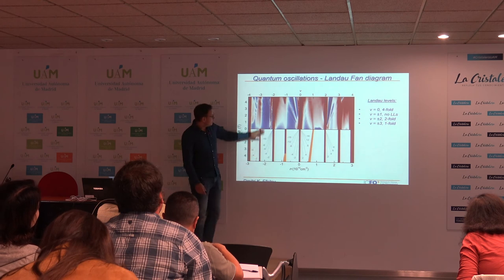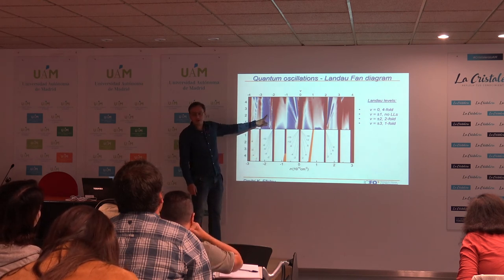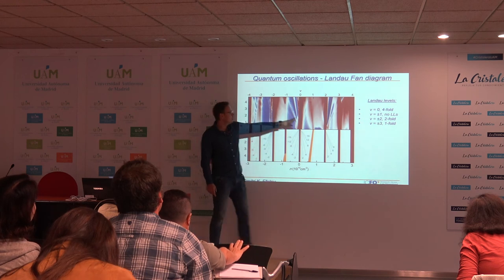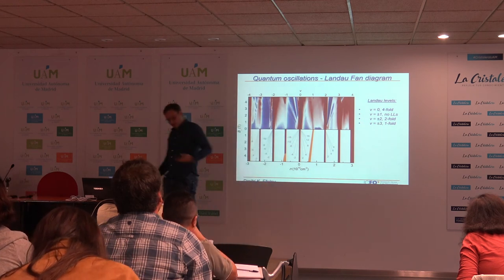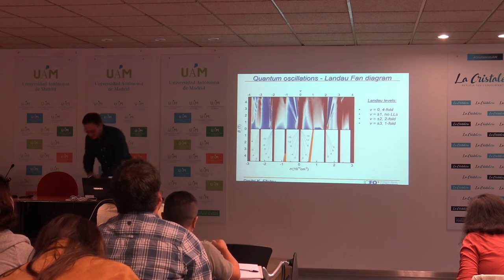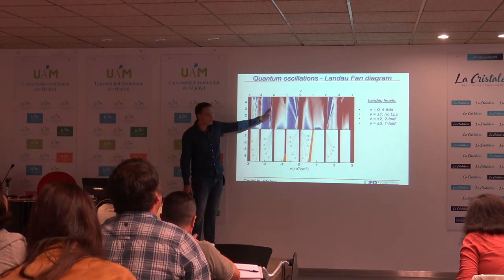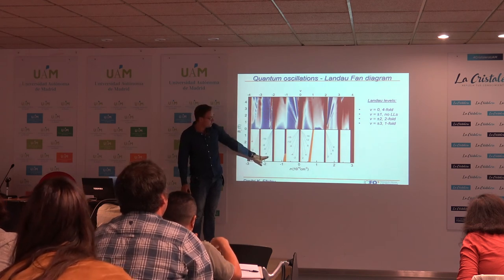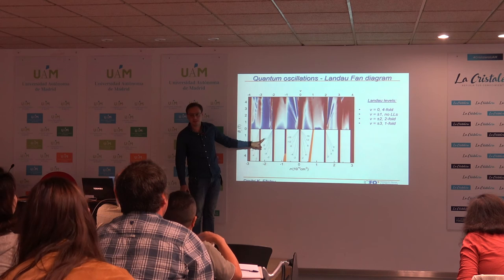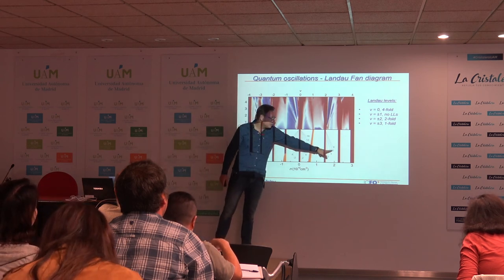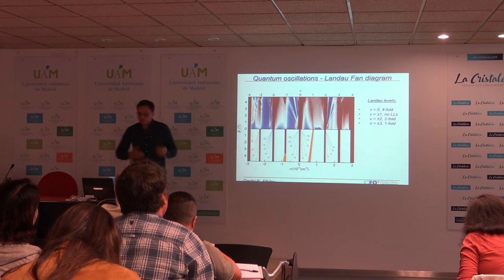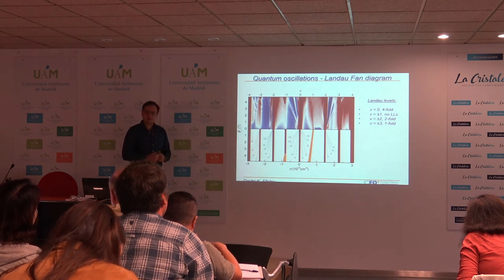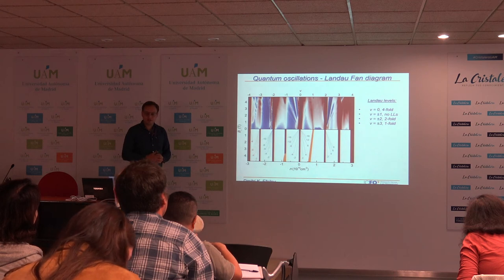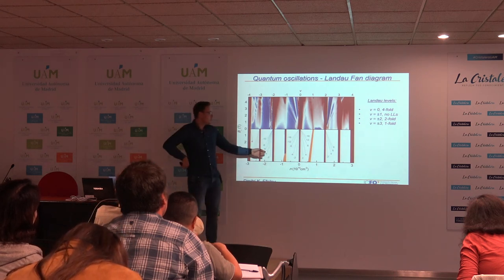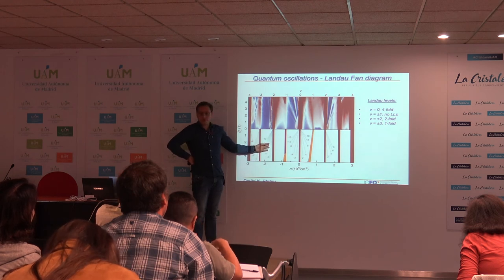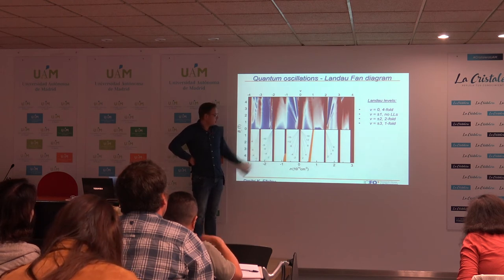But then we also see Landau levels originating from the correlated insulating states, from the minus 2 state here and from the plus 2 state. And if we look at the degeneracies of these Landau levels, we find degeneracies of minus 2, minus 4, minus 6, minus 8, minus 10, and also the same here, 2, 4, 6, 8. So basically we already know that in these Landau levels we can pack half of those electrons as close to charge neutrality, so that's already an indication that either spin or K degree of freedom is broken here. So the underlying symmetry of these bands is different.